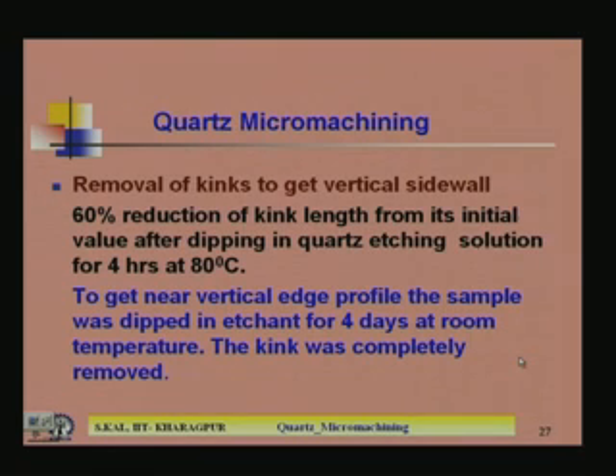Just, we can conclude here that removal of kinks to get vertical sidewall is an important issue. 60% reduction of kink length from its initial value after dipping in quartz etching solution for 4 hours at 80 degree centigrade. To get near vertical edge profile, the sample was dipped in etchant for 4 days at room temperature, and the kink was completely removed.